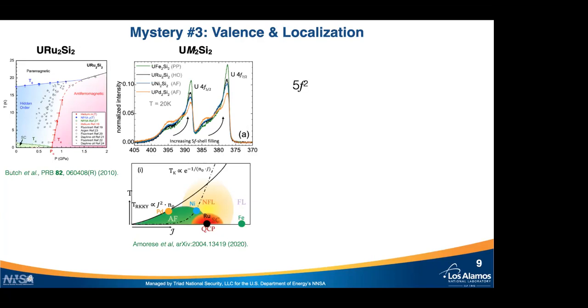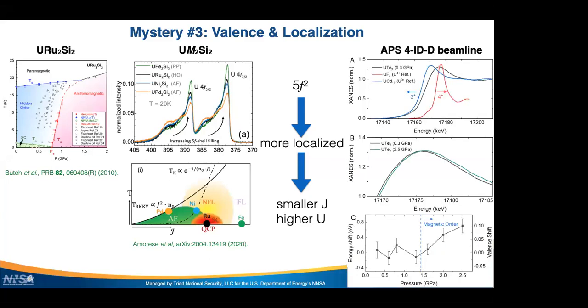So the point here is that for the 5f2 state of uranium, the f electrons are more localized and you have smaller J's, again, thinking of the Doniach phase diagram, or even higher U, which is the on-site Coulomb interaction. So taking this to UTe2, we have done in collaboration with Gilberto Fabbris at the Advanced Photon Source facility, measurements on UTe2 under pressure.